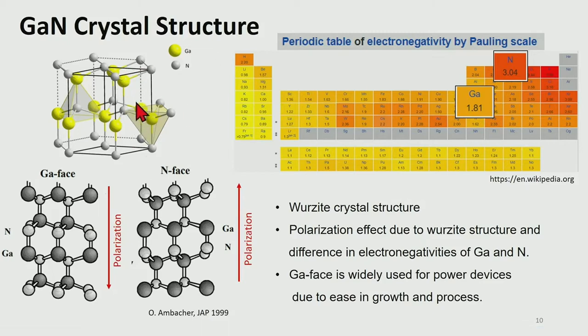And as you can see in this left figure, the gallium and nitrogen atoms are arranged in closely spaced hexagonal bilayers. If the gallium is on top of the bilayer, it is called a gallium face. If nitrogen is at the top, it is called a nitrogen face. And typically, the gallium face is mainly used for power devices because it's much easier to grow and process.